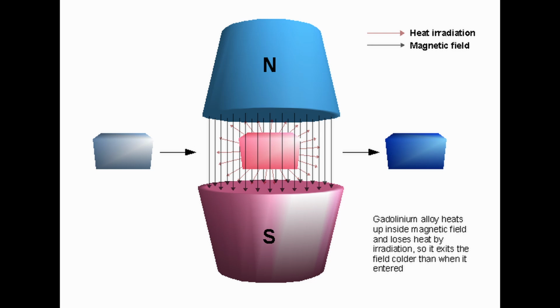Now, since then, we found other alloys that show this giant magnetocaloric effect. There are variations of the gadolinium silicon-germanium mix, some lanthanum iron silicon hydrogen compounds, and also manganese iron phosphorus arsenic compounds. The problem is that many of these rely on rare earth elements like gadolinium, which are expensive, making them less appealing for widespread use. So cost is a factor here. Are there any other options that might be more affordable?